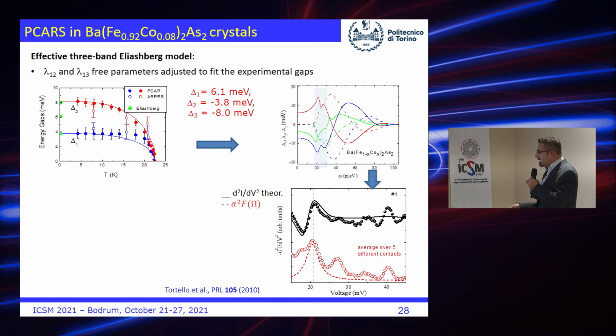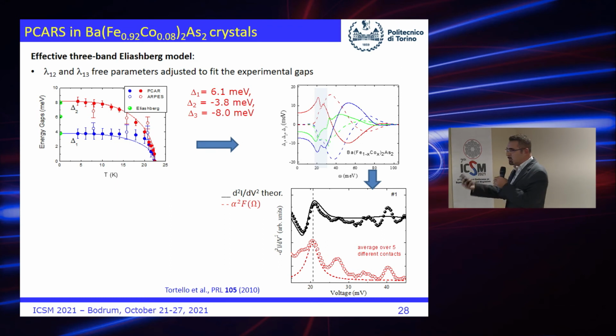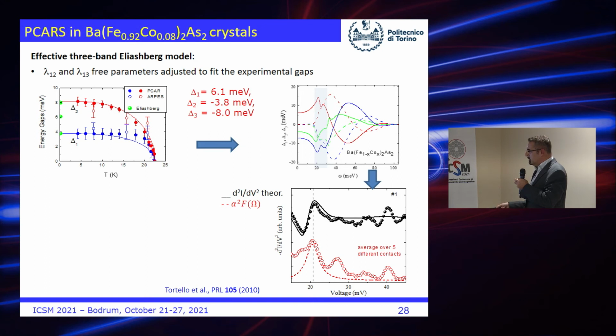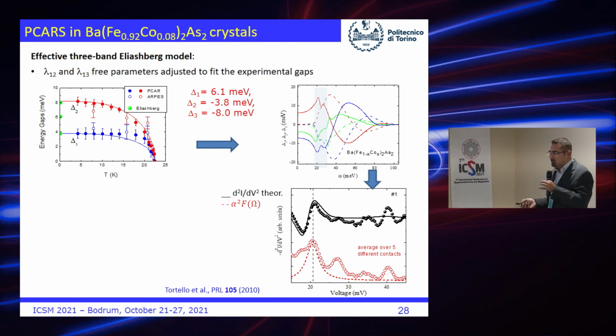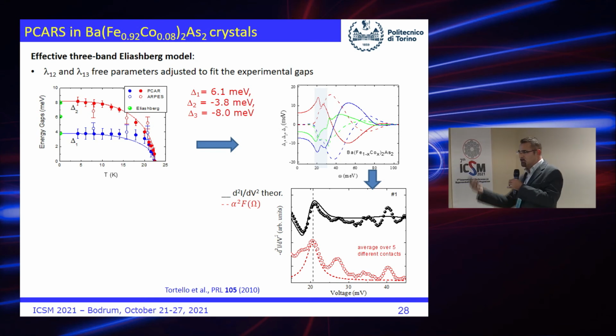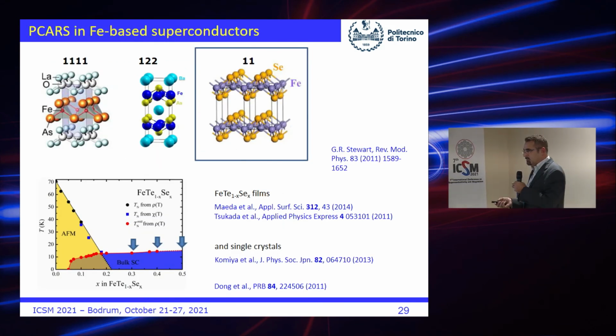Again, if I make the average over 5 different contacts on the same kind of sample, I obtain this curve, this is the second derivative, and I could compare it directly with the alpha square F, that means with the Lorentzian I chose, and they fall exactly in the same position. So this is a rather convincing proof of the fact that either way you see it, you start from the boson and you calculate the spectra, or you start from the spectra, you calculate the boson, you obtain a rather good agreement. I also have data, but I think I do not have time, in iron, selenium, tellurium.